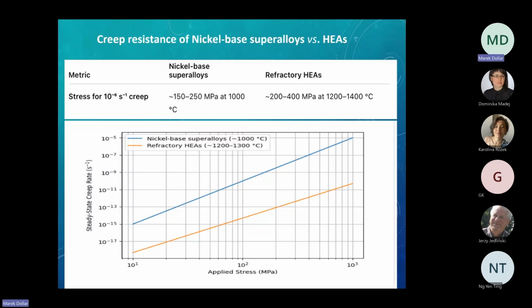The lower the curve, the slower the diffusion, the better creep resistance. Despite the fact that the temperature difference is so significant. We're talking 2 orders of magnitude, even 3, slower diffusion. So creep time, in practical terms, if the creep rupture time in a nickel-based alloy is a matter of months, in high entropy alloys, 2 orders of magnitude, we would be talking tens of years.